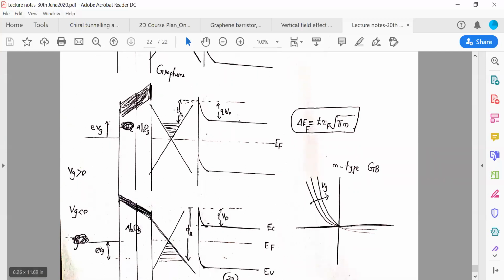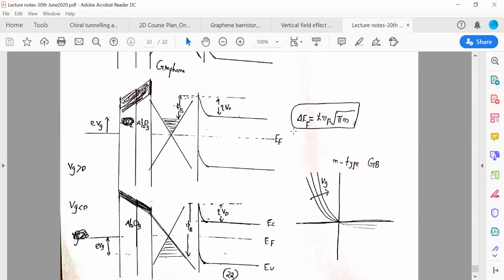Now, an important point is how much Fermi level shift you can induce, what work function change you can induce. That all depends on the carrier density you can induce using a gate. For example, in single layer graphene, you can induce up to 500 millivolts. This is because the conical, linear dispersion allows you to move the Fermi level faster than the parabolic one. In the case of parabolic dispersion, this change will be smaller. But because of the linear dispersion, you can change your Fermi level much more, up to 0.5 electron volt, or 500 milli electron volt.